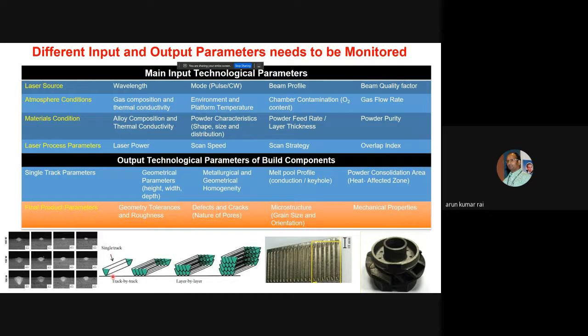Suppose we deposit, you can see we deposit first a single layer, okay, then we overlap and deposit a single layer, meaning first a single layer and then multi-layer on a single platform. So you can see the overlap of the laser beam. Sometimes if you are excessively overlapping or under-overlapping, this can lead to defect formation in the metal. So this has to be optimized before printing the final product in 3D like this. So you can see one of the actual examples I am showing here.